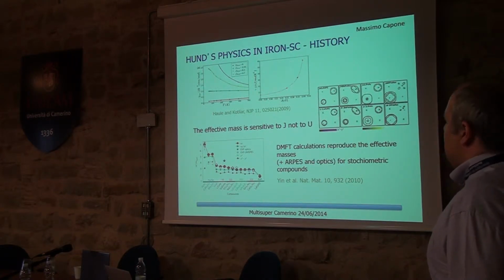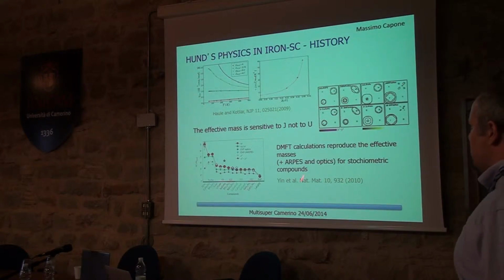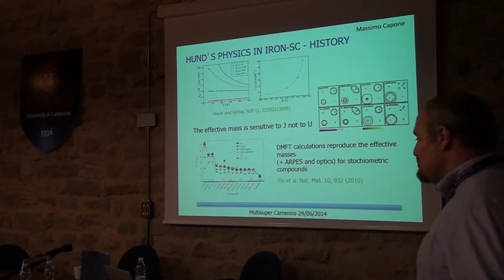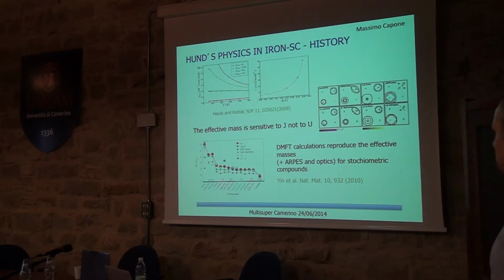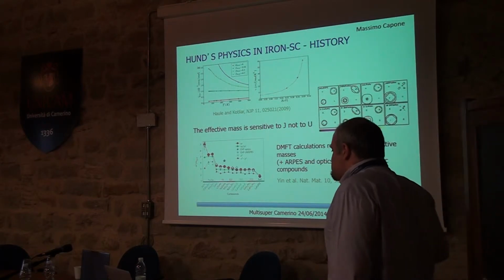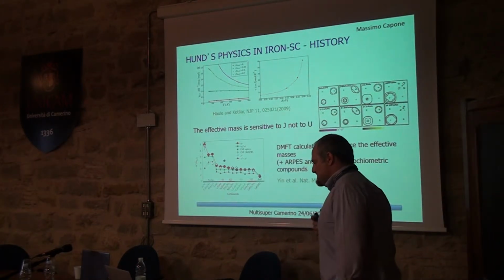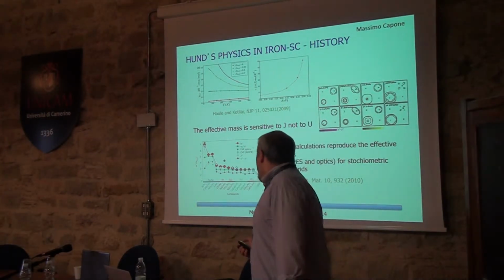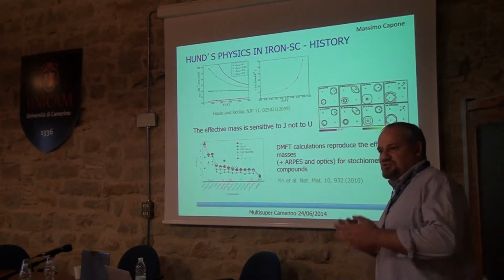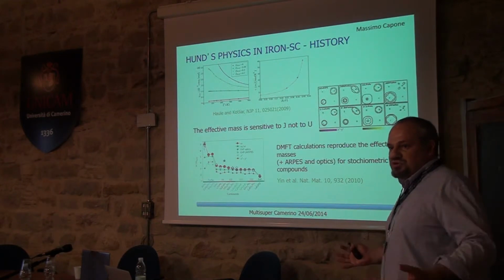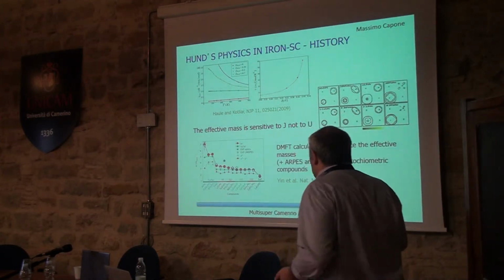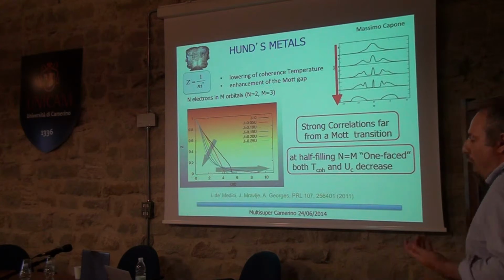And the other thing you learn is that if you play this game and choose reasonable values of J and U, then you are able to reproduce the effective masses of a variety of undoped iron-based superconductors, and also many features of the photoemission. So it turns out that everything depends a lot on the Hund's coupling, and this dependence brings you to the right place. You reproduce what happens in the experiment. So the natural question is, of course, why?